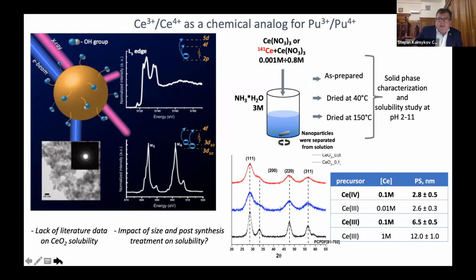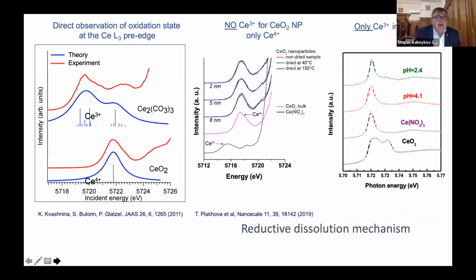Is it due to the Ce(III) present in the structure, or are there some other effects? So again, we made all these precipitations, we made the X-ray diffraction, and the size, again, not like in the case of plutonium, was dependent on the concentration of cerium, and it was dependent on what we take as a precursor, either Ce(IV) or Ce(III). So the size was quite different, from, let's say, 2.8 nanometers up to more than 10 nanometers in size. So this is again not like in the case of plutonium. So we made L3 edge measurements to characterize the colloids, the particles there. There is no evidence of Ce(III) in the structure of CeO2 nanoparticles. Independently of the particle size, from 2 nanometers to 8 nanometers, we don't see any presence of Ce(III) in the structure of these nanoparticles.